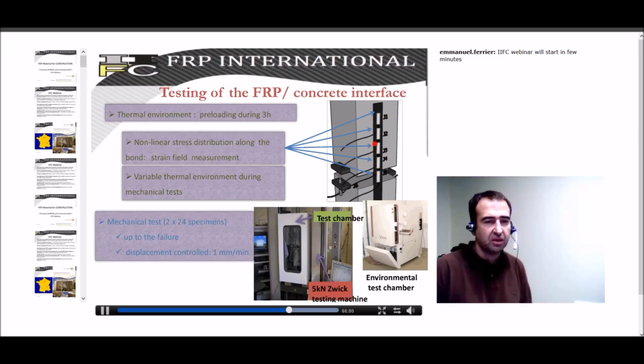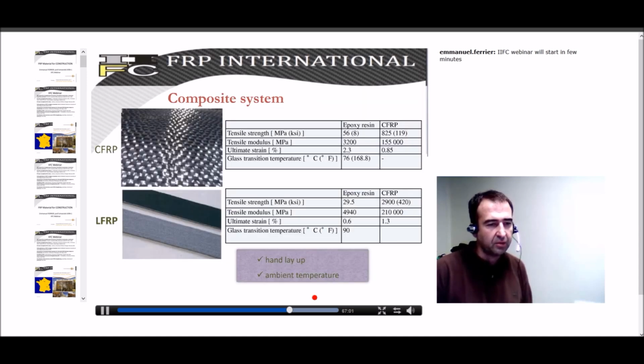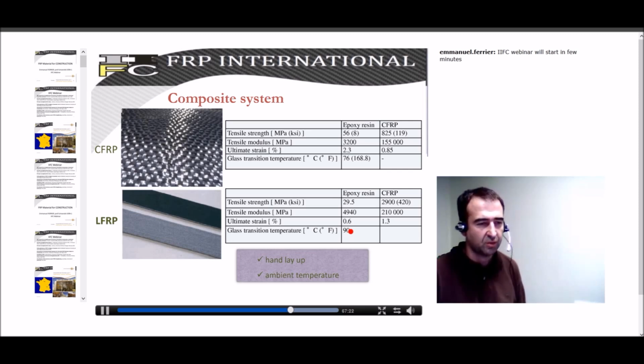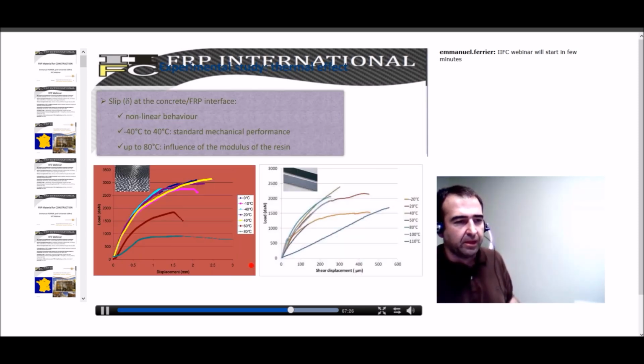To identify the way that strain decreases along the bonding length, we have bonded several strain gauges, allowing us to get the full strain in the FRP and then to get the load transfer. In this study, a wet layup system was used with carbon fibers, and laminates were bonded onto the surface, with two different properties. This one has quite a high glass transition temperature, which was very interesting in this study. Then, an example of results obtained, for example, with the wet layup method, you have here load and displacement.